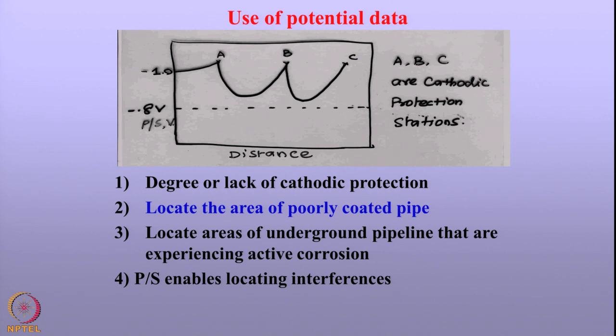The potential data is very useful on several accounts. One, as we discussed now, it indicates the degree or lack of cathodic protection of the pipeline. It can indicate the protection capacity of the coatings, if the coatings are damaged or degraded. Now, you can also look at those underground pipelines which are experiencing active corrosion or suffering interference, stray current corrosion. If the potential remains above minus 0.85, it indicates that any of these cases are responsible for the corrosion of the pipelines. So, thank you.